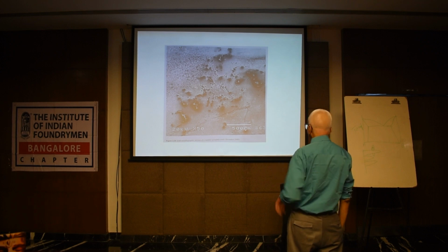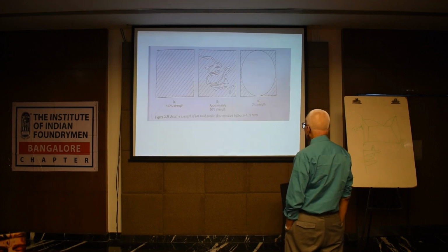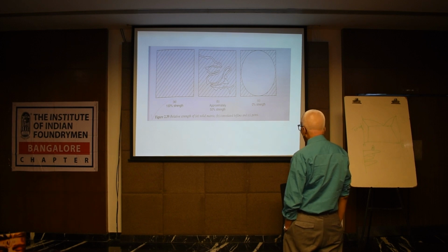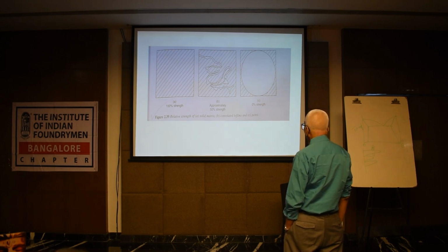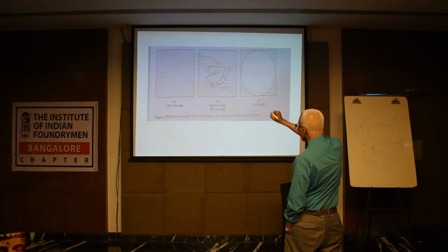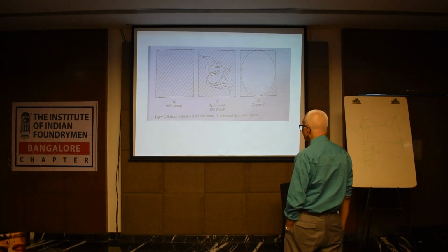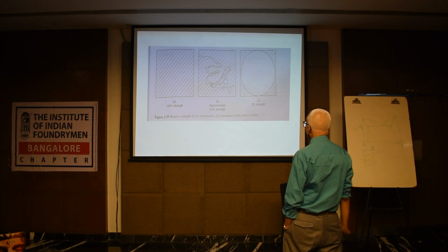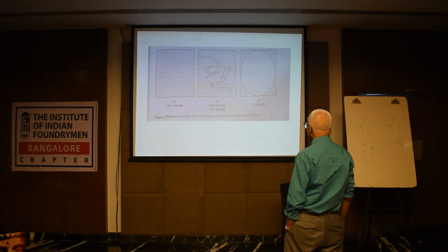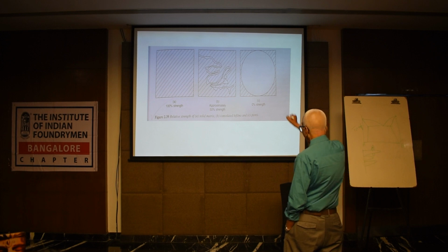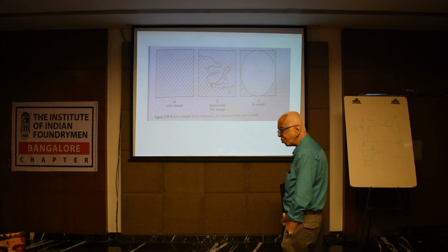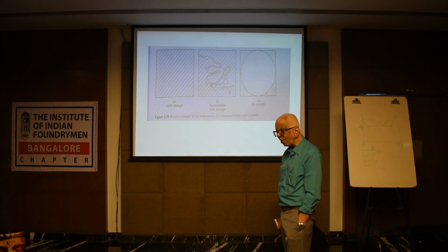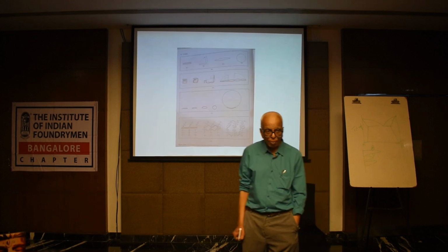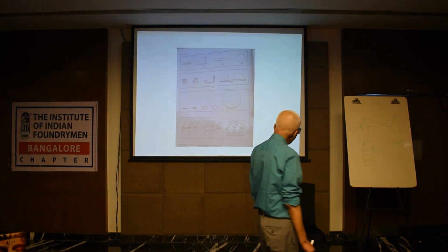The entrapped gas inside. Next slide, please. Yes. Now, these are pores. Suppose you don't have any defects in the casting, you have 100% strength, and then once you introduce bifilms, properties drop. And such a big void in the casting is very susceptible to failure.